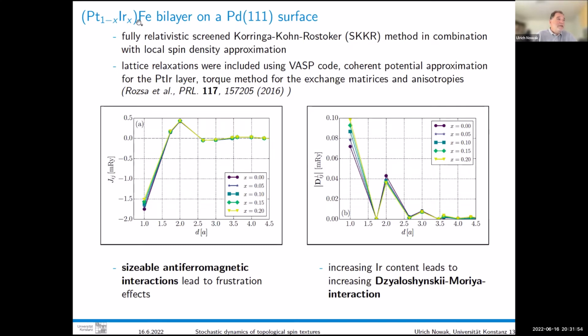And for a specific material, and this is our workhorse, you could say, that is an iron layer covered by platinum iridium on a palladium surface. Here you get a lot of Dzyaloshinskii-Moriya interaction because of the symmetry breaking and the large spin-orbit coupling. And you can calculate all these interactions from the Hamiltonian that I showed you on the slide before. And it looks a bit like that.